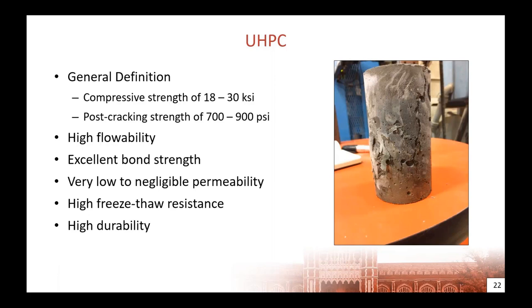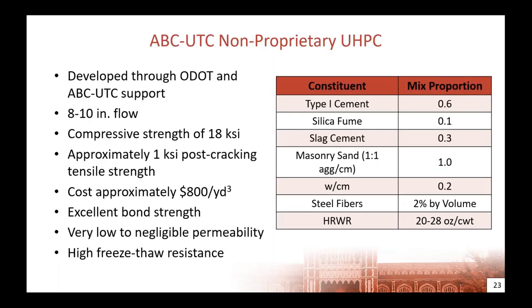a resulting high durability. There are a lot of UHPC products that are available on the market these days, proprietary mixes from various manufacturers, as well as non-proprietary or open source type mix designs, including one developed in conjunction with the ABC-UTC that I provide here as an example, not necessarily used on all of this project, but throughout in various places. We developed a mix with the Oklahoma DOT and ABC-UTC that's shown here on the right as a weight proportion. So one-to-one cement to sand ratio, 60% of the cement was type 1, 10% silica fume, 30% slag cement, and a water cement ratio of 0.2.